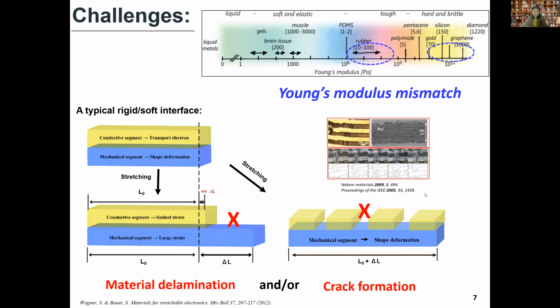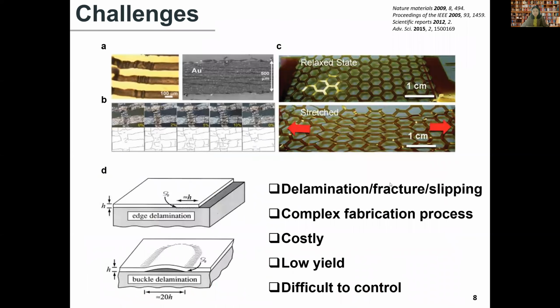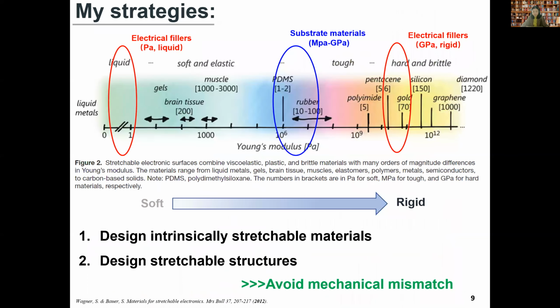The challenges in soft electronics will be presented in this slide. There are basically two components: the soft mechanical component, made from soft polymer materials, and the electrical component, made from active electrical materials, which are metal or carbon-based materials. These two materials have a very large mechanical mismatch, which leads to delamination or fracture when the device is stretched. So in order to avoid the mechanical mismatch, my strategy is to develop novel materials and integrate them with structural engineering to make devices that can be stretched.